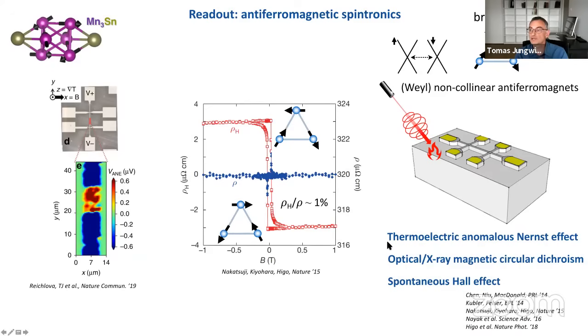And similar to anisotropic magnetoresistance, I'd like to emphasize that you can have the optical counterparts of the Hall effect, which is called the magnetic circular dichroism. And you can also have the thermoelectric counterpart, which is called the spontaneous or anomalous Nernst effect. So here we have an example of a recent study which used the anomalous Nernst effect in combination with focused laser spot local heating, again, to generate an image of domains in this non-collinear antiferromagnet manganese tin.